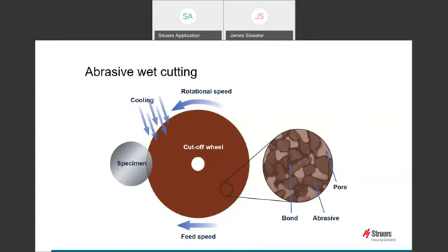The cutting wheel consists of abrasives, bonding material, and pores. Deliberate changes to the bond strength and the pore spacing change the properties of the cutting wheel to enable a wider range of hardness of material to be cut cleanly and efficiently. These differences in pore spacing and bond strength are also within the wheels themselves, which ensure a reproducible and consistent cut every time. It's all too easy to assume that all cutting wheels are equal. Selecting one grade for everything can often lead to poor wheel performance and additional work requirements to clear up the damage caused during the cutting operation.